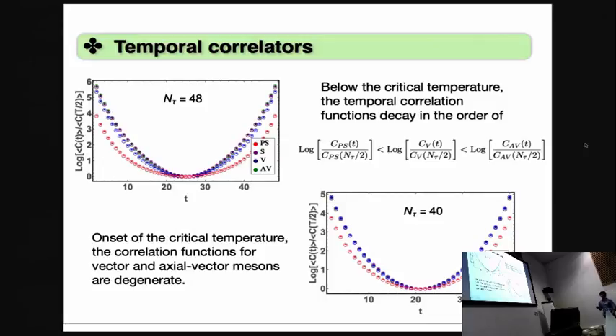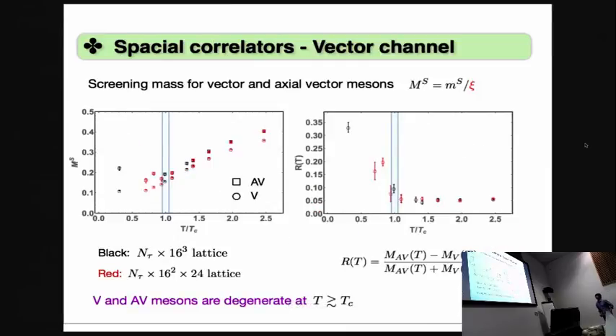Okay, so let me show you the temporal correlators. This is a result for N_tau equals 48, which is below the critical temperature. The basic features of these temporal correlators are the same as at zero temperature, where the pion decays very slowly, while the vector meson, axial vector meson and scalar meson decay quickly. Then as you increase the temperature, or decrease N_tau, at N_tau equals 40, which is the onset of the critical temperature, we found that the vector meson and axial vector meson are degenerate. This is evidence of the degeneracy, the higher symmetry restoration.